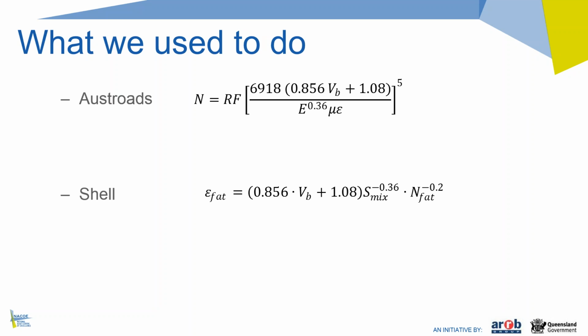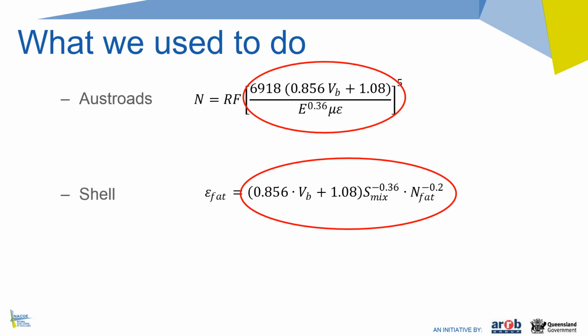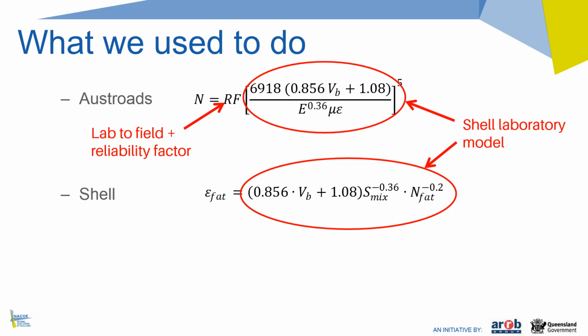You'll notice that that is very similar to the shell equation that is shown at the bottom of the page, which is based on, actually it's exactly the same. So that shell equation was developed, it's a laboratory model, it represents the mean performance of 12 mixes tested in the 1970s in Europe, based on mixes from different countries, but all overseas mixes, none from Australia. So this part, the last part of the Austroads equation and the shell fatigue relationship are the same. They provide exactly the same outcome. So the shell laboratory model is currently used in the Austroads fatigue equation, and all we do is we have a shift factor to shift the laboratory performance to field performance.